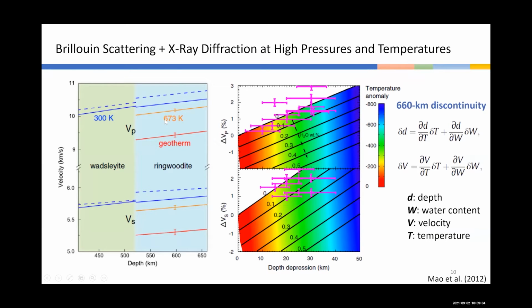Once we know the sound velocity of hydrous ringwoodite, we get the depth variation of the 660 kilometer discontinuity, and then we try to estimate what is the water content at the bottom of the transition zone. I'll just quickly go over this work. From this work, we see that at most places of the bottom transition zone, the water content is very low, less than 0.1%. So this is the first example that I want to share with you, where we use this facility to study the mantle composition.